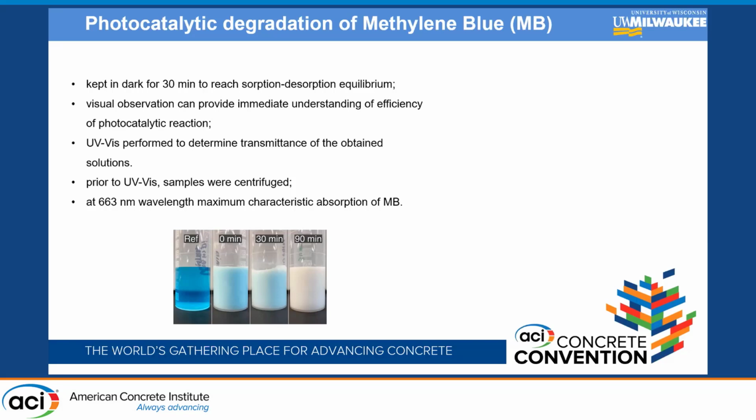minutes is the same sample. One was centrifuged for the purpose of the UV-Vis test, which will be performed later. We can see at 0 minutes, the sample is pretty bluish. After 30, we are decreasing, we are losing some color, and after 90 minutes, we don't have any methylene blue present in the formulation whatsoever.